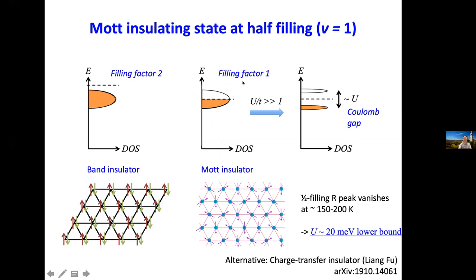So in the limit when U/T is very big, a Coulomb gap opens up, and our result is consistent with the Mott insulator picture. From the temperature dependence of that peak, which disappears around 150 to 200 Kelvin, that gives us a lower estimate of how big this U is - on the order of 20, but later measurements show that this is bigger than this number.